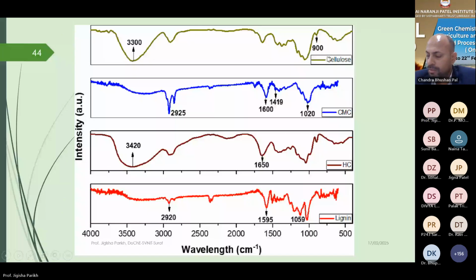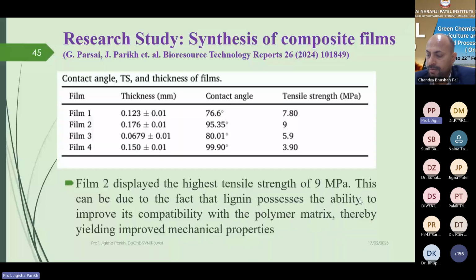Okay, this is confirmed by these FTIR methods through these bonds. Then this is the carboxymethylation product of the cellulose, that is the carboxymethyl cellulose. Okay, then this is the hemicellulose which has been fractionated, and this is the lignin material which has been isolated. Okay, so we have received the pure material from the fractionation, and then those materials were utilized in the formation